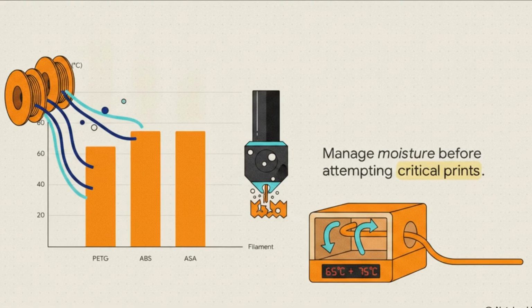Finally, let's drill down real quick on tip number 3. PETG, ABS, and ASA are all hygroscopic, which means they eagerly absorb water molecules straight from the ambient air in your room. If you don't dry them before printing, that trapped water actually boils inside your printer's hot nozzle. No joke, this creates tiny explosive steam bubbles that completely destroy your part's internal layer structure. You absolutely need to manage moisture in a filament dryer before attempting critical prints. Specifically, you're looking at 65 degrees Celsius for PETG and 75 degrees for ABS and ASA. Doing this prevents those hidden steam voids and guarantees nice, strong, clean extrusion.